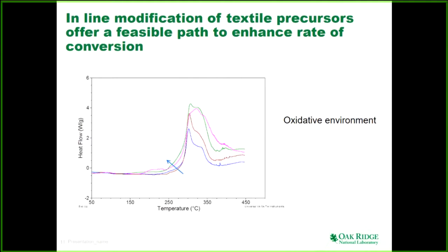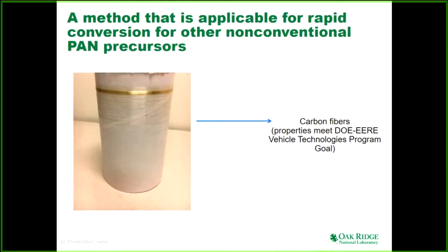Now, is this applicable to any other precursors? Yes. As long as it sees a PAN molecule, whether you have a textile-based PAN or specialty acrylic PAN, these chemistries are applicable. And in fact, this is a spool, of course a very tiny spool, of monofilament we produced in our lab. This was done by melt spinning. We applied that to melt spinning of polyacrylonitrile, and we produced carbon fibers that meet the lower target. Of course, the Vehicle Technologies Office of EERE's target is very low, 250 KSI, 25 MSI type performance. But we can make that kind of carbon fiber from these modified PAN precursors. In these cases, however, we did not use any rheology modifier that I mentioned earlier.